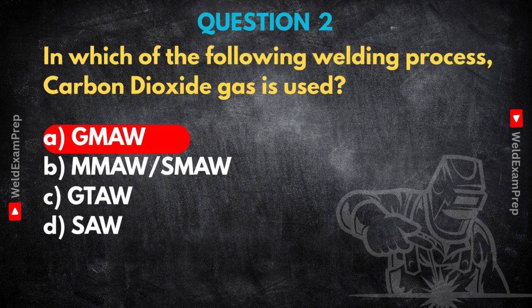So why CO2? Well, unlike argon, which is inert, CO2 is actually a reactive gas. That means it gets involved in the arc chemistry. When you use it, especially with certain transfer modes like short circuit, it tends to give you really good penetration into the base metal. That's a big plus for thicker stuff. What happens is the CO2 breaks down in the hot arc into carbon monoxide and oxygen. This reaction actually helps stabilize the arc and makes the weld pool hotter, which improves fusion and gives you a strong weld.